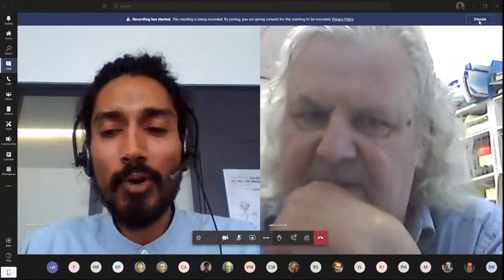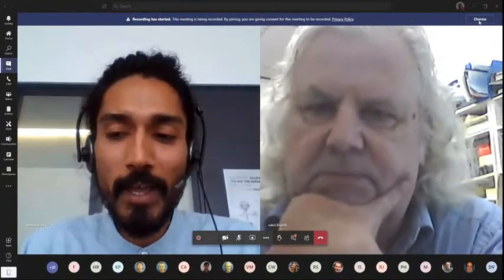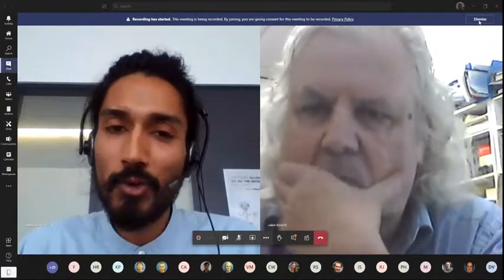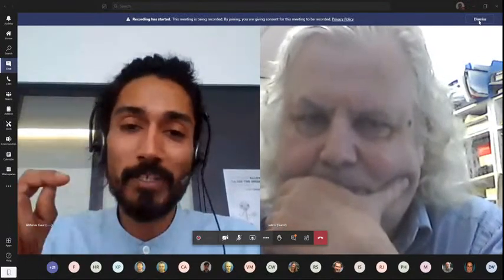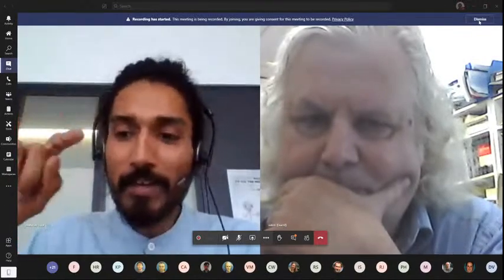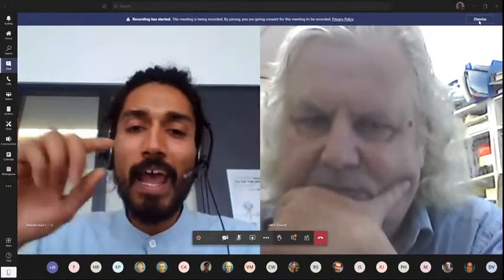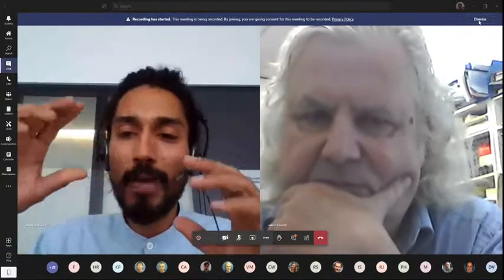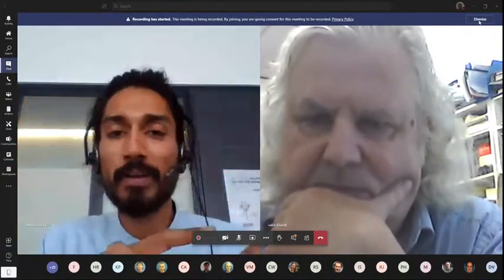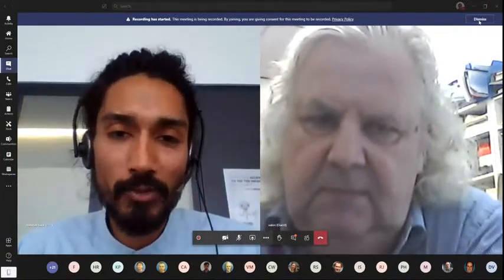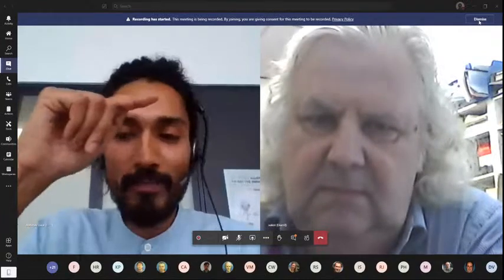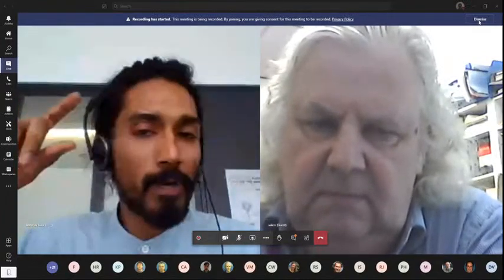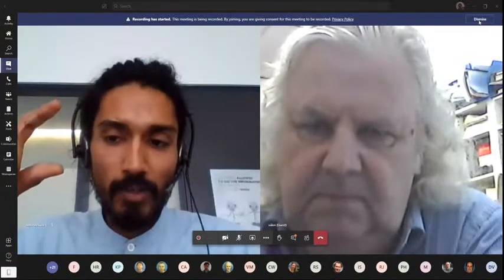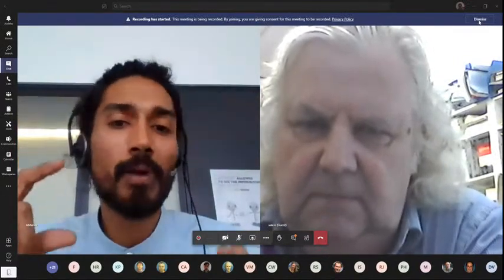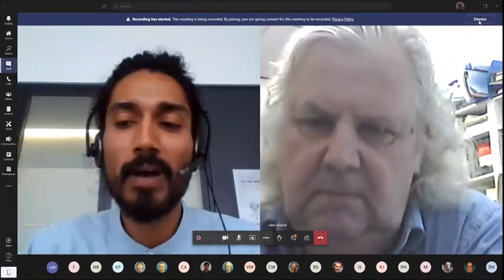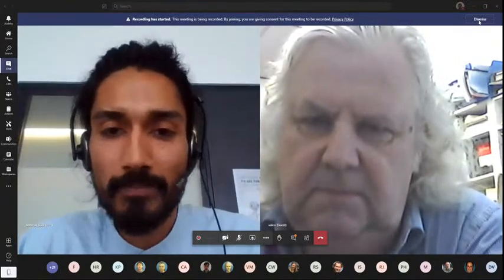The DIT remains more or less consistent in these two devices, but in literature, we also saw that if there is a surface roughness, as in a corrugated surface, that leads to a very rough interface, right? And the major problem of band gap reduction and expansion was in the valence band. So I would like to say that we are not directly measuring those sorts of things. We are mostly measuring things in the conduction band, where we also see some fluctuation, but maybe that's not very strong. So for sure, roughness will have some sort of impact, but exactly how much, I think that's still masked by the property of the channel.